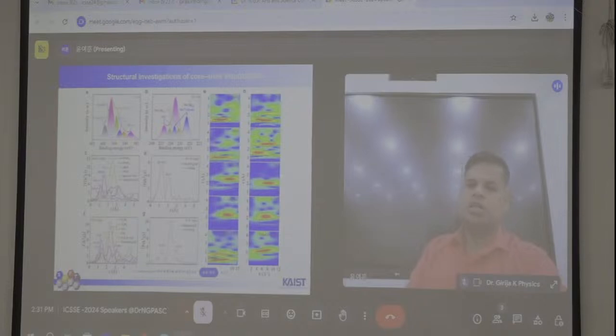And finally, the WT-EXAFS analysis also clearly shows the R value is lower than 2 in the case of the optimal catalyst compared to the foil. The foil has the metal bonding, and similar observations are seen for the vanadium case. And after confirmation of the structural and morphological investigation, we are doing the 3-electrode test for the ORR and OER tests.